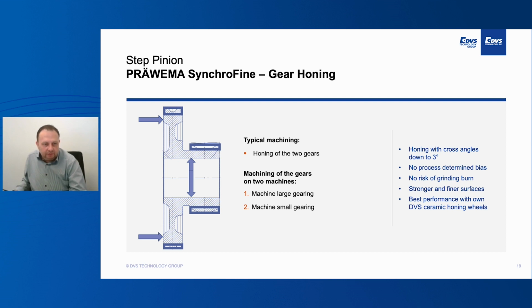The honing process itself is working, what we say, with the X-cross angle bigger than 3 degrees absolutely safely. For the step pinion, we had to push and create solutions so that we are able to hone also with the limit X-cross angle, which is a little bit lower than 3 degrees. You will get all the advantages of the honing process. That means you will not have bias out of the process, which comes from the grinding process, but you can do the bias by programming. There is no risk of grinding burn for the gear because the cutting speed is around 10 to 12 meters per second. Grinding burn is to be expected from a cutting speed which is higher than 18 to 20 meters per second.